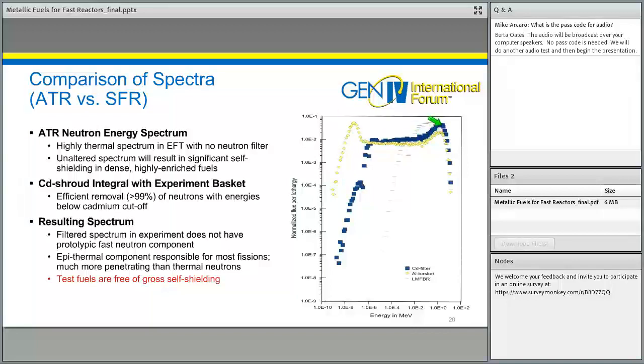So that's what you see here in the blue. You still have your high energy fission spectrum. You have a lot of epithermal neutrons, but then the thermal neutrons below the cadmium cutoff are essentially entirely removed from the test fuel. We're able to achieve greater than 99% removal of thermal neutrons seen by the test fuels. And what that altered spectrum does is it certainly doesn't change the test spectrum into a prototypic fast neutron spectrum. It doesn't do that. But what it does is it eliminates the thermal neutrons.